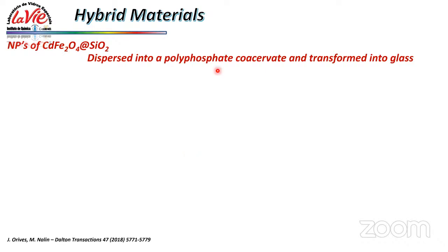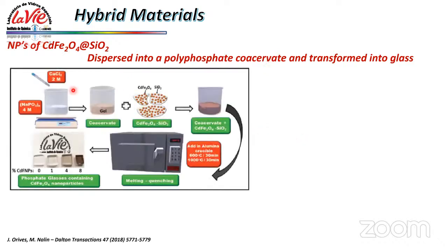For this, we use polyphosphate coacervate, which is a phosphate that can be transformed into glass, and it's obtained at low temperature. So we use a solution of sodium polyphosphate, and we add to this solution another solution of calcium chloride. After one concentration here, it will form a gel that is the coacervate. There is a phase separation here. Then we dry it, and we add the nanoparticles to the coacervate, and we melt this coacervate in a furnace for some minutes to eliminate water, and then we can obtain glass, with different contents of nanoparticles.